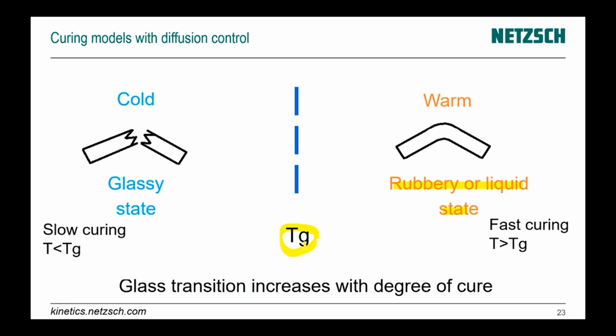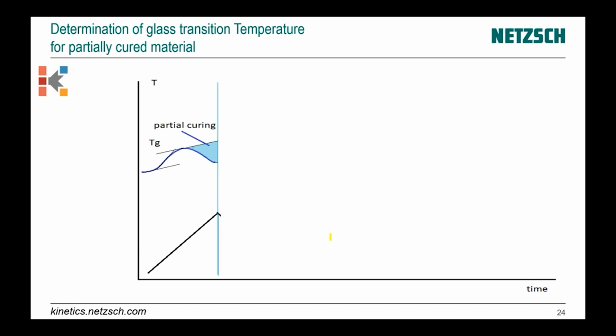If you make the curing analysis, then we must take into account that for the glassy state we have slow curing, and for the rubbery or liquid state, for temperature above glass transition, we have fast curing. And we must take into account this during simulation, but firstly we must know where the glass transition is for the current degree of conversion. In order to find this dependence, the following measurements normally are done.